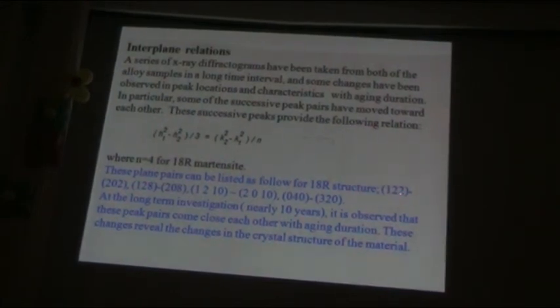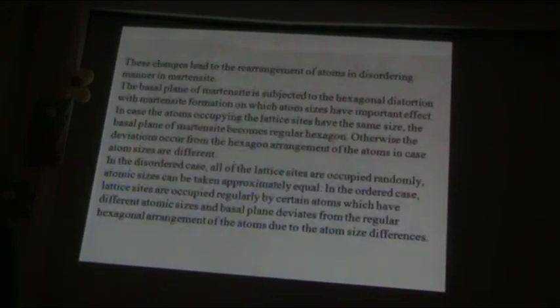In the long-term investigation, nearly 10 years, it is observed that these peak pairs come close to each other with aging duration. These changes reveal the changes in the crystal structure of the material.